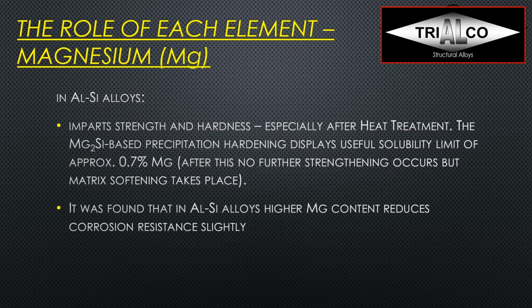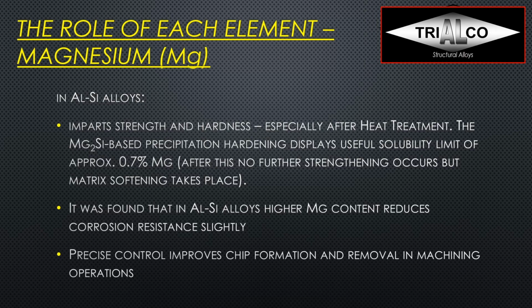It was also found that in aluminum silicon alloys, higher magnesium content reduces the corrosion resistance slightly. So you have to be careful with that. And precise control improves chip formation and removal in machining operations.